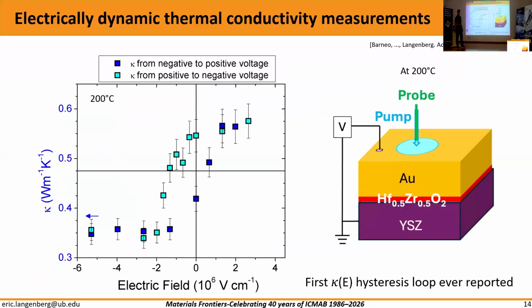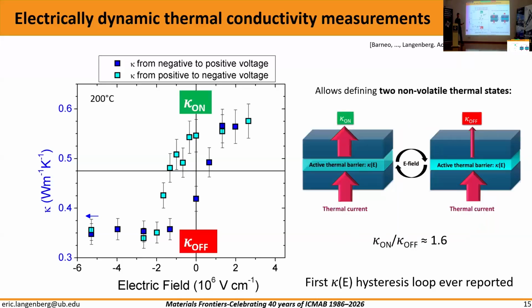And then this is actually the result. Here we have the thermal conductivity as a function of the electric field. And it's actually the first hysteresis loop that we have got. Actually, I haven't seen anyone report thermal conductivity versus electric field. So the dark blue dots go from negative electric field to positive electric field, and the light blue dots are the way around. This means that it allows defining two thermal states, high and low thermal conductivity, on and off.